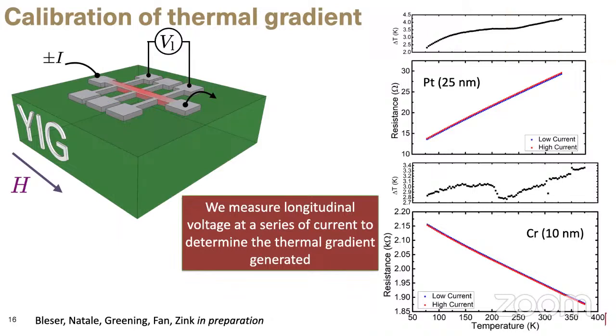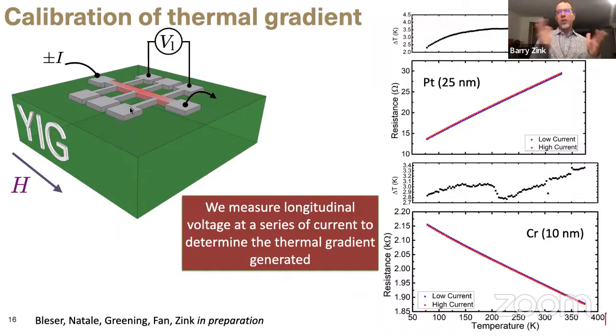Sorry, but how did you get the actual temperature? How do you get this conversion plot? We measure in two different geometries. All of the data that I showed you is measured where we're taking the Hall signal, so we're measuring the transverse voltage in response to the current that's going down the strip in the middle of the Hall bar. Then to understand the resistance of the structure and map that back to temperature, we measure the longitudinal voltage of the structure. That's just to measure the resistance, and then we apply the exact same current that we're going to use in the experiment.